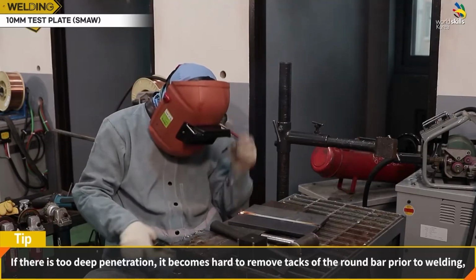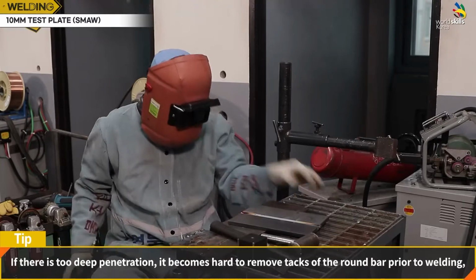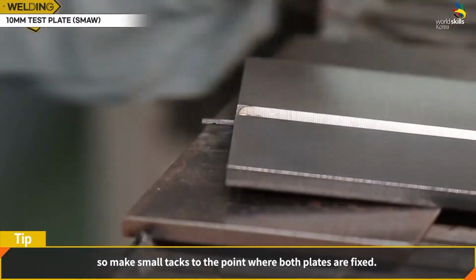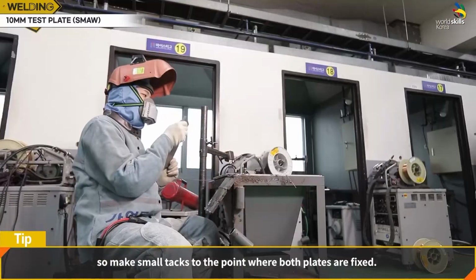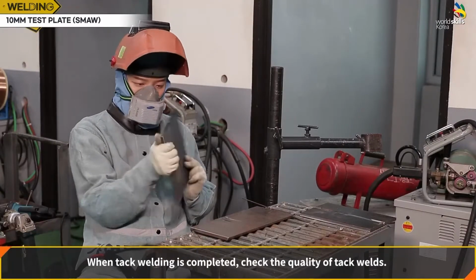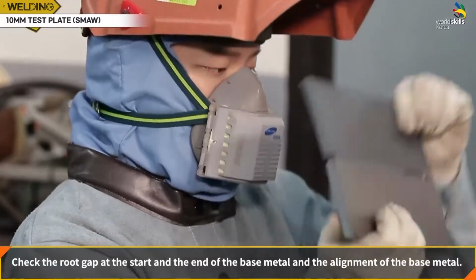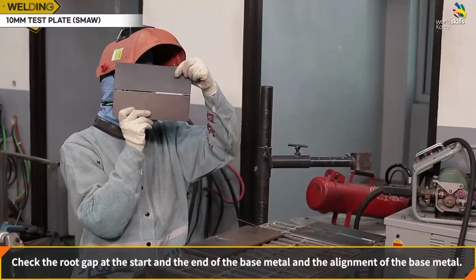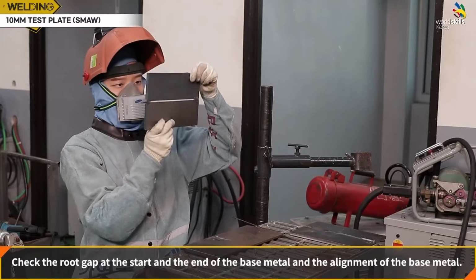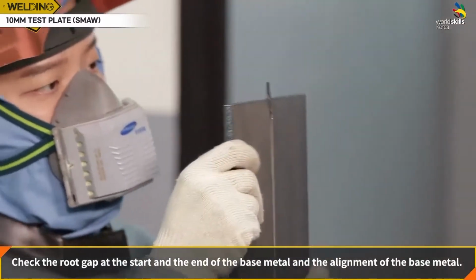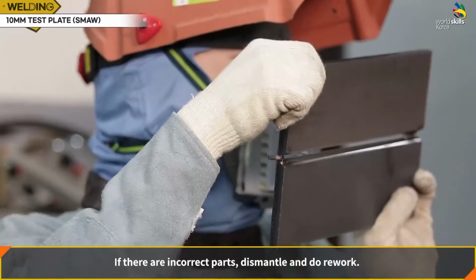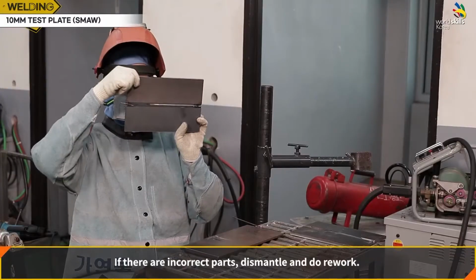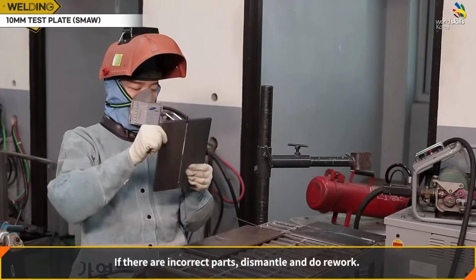If there is too deep penetration, it becomes hard to remove tacks of the round bar prior to welding, so make small tacks to the point where both plates are fixed. When tack welding is completed, check the quality of tack welds. Check the root gap at the start and the end of the base material and the alignment of the base material. If there are incorrect parts, dismantle and do rework.